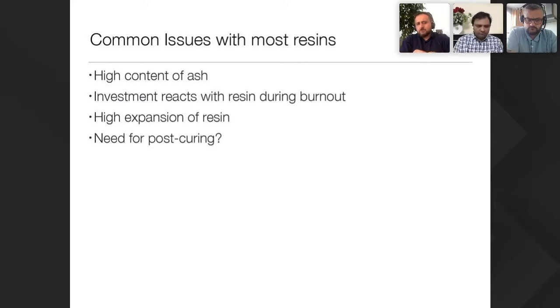And when we look at the most common issues with most resins on the market, first of all, you have a high content of ash. So even if you burn it at 700 or 800 or 900 degrees, you still have this ash component that stays in the resin. That's not the only problem, by the way. The other issue that most resins have is that during burnout, when the temperature is going high, the resin is reacting with the investment wall.